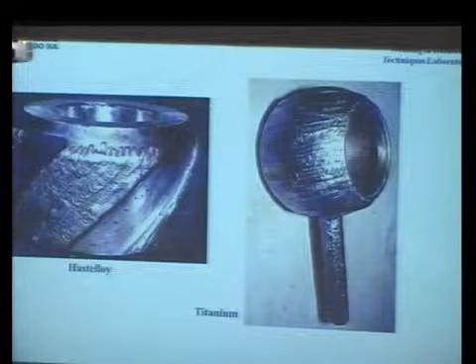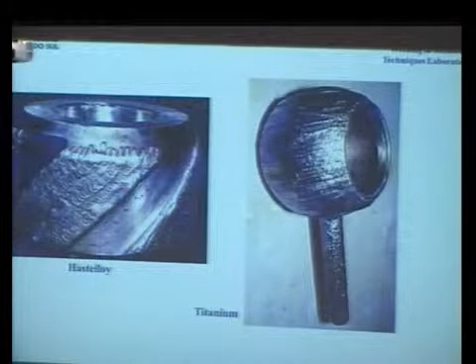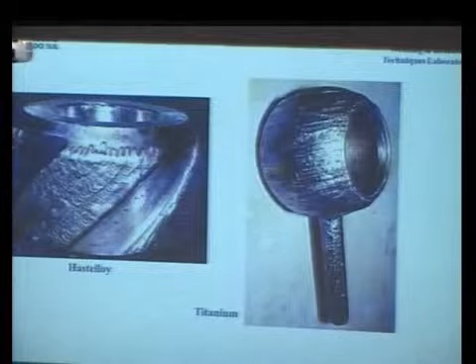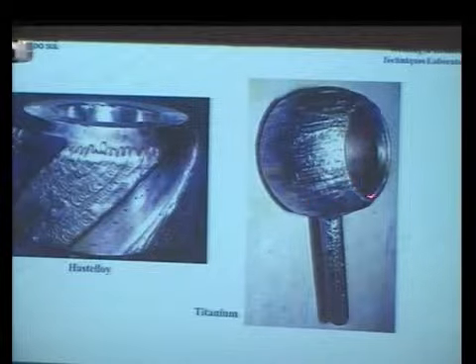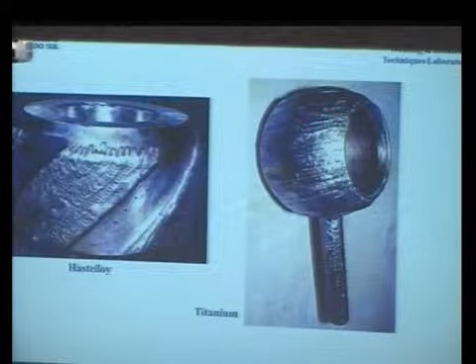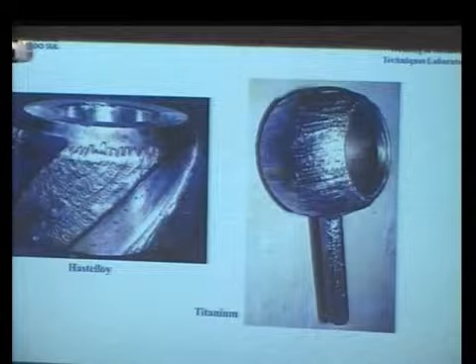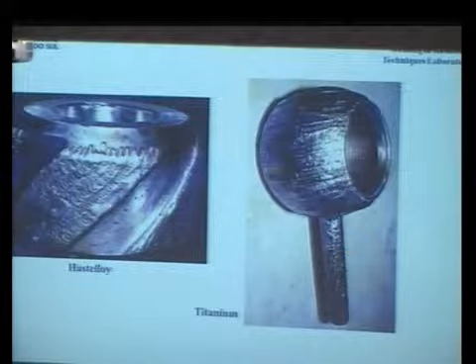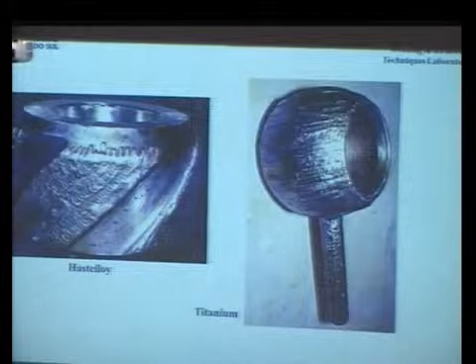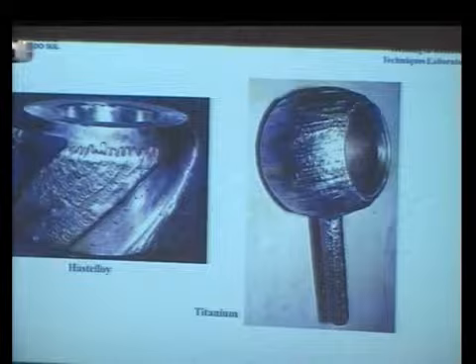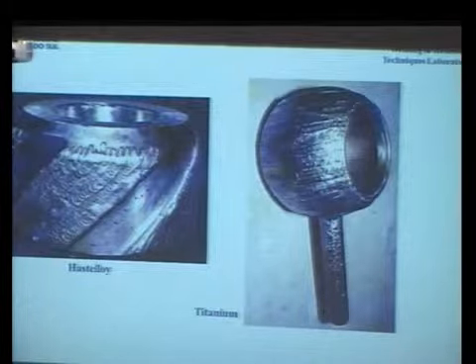Well, in the past, we used to weld for third parties different alloys that were difficult to weld. Nowadays, many people that pass through our laboratory know how to weld difficult alloys, titanium, for example. On the other side of the river, Guaíba, for those of you who are not from here, there is a big cellulose factory. And they use those valves, that's a valve. With time, the acids attack the surface of the valve. And then you have to weld it all again. It's commercially pure titanium. You have to make a chamber with high purity argon. It's very expensive, this one. And weld during one day, things like that.